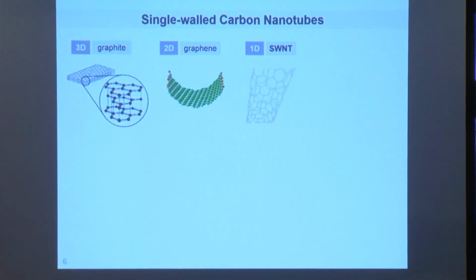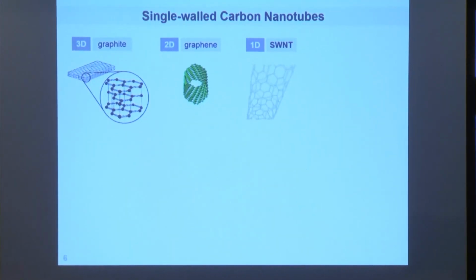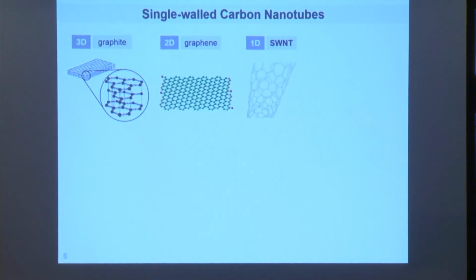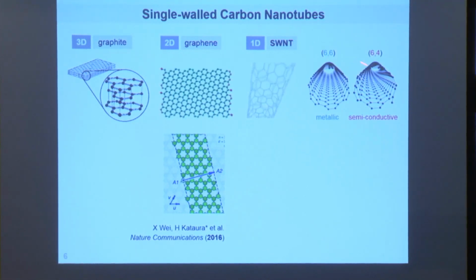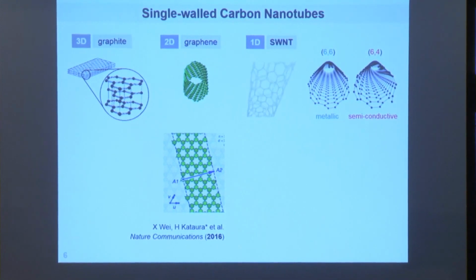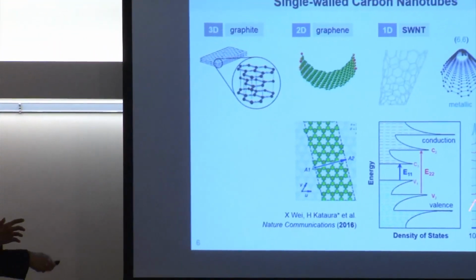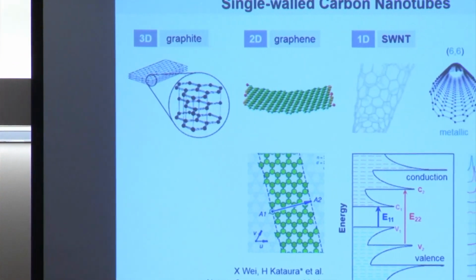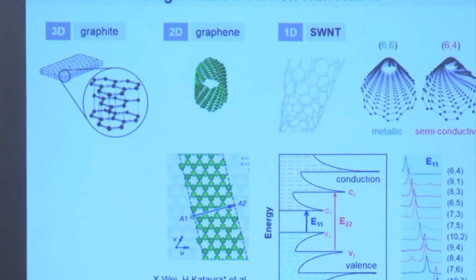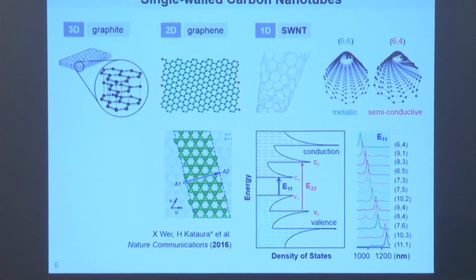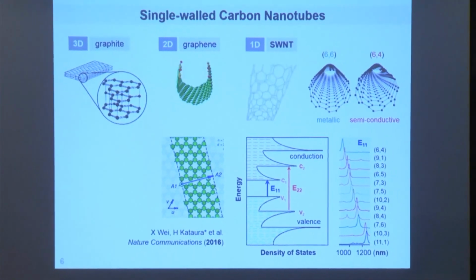And so as previously alluded to, we use carbon nanotubes in our lab. And one of the fascinating things about carbon nanotube, which, by the way, you can think of them as rolled up sheets of graphene. If you think about that way, you generate carbon nanotubes of different chirality, depends on how you rolled up your sheets of graphene, and you get different sort of electronic structure, this tunable band gap, which is nice because this is the model compound that we can use to test some of our theory and to probe the generation mechanism of the microscale electricity generation concepts that we have.